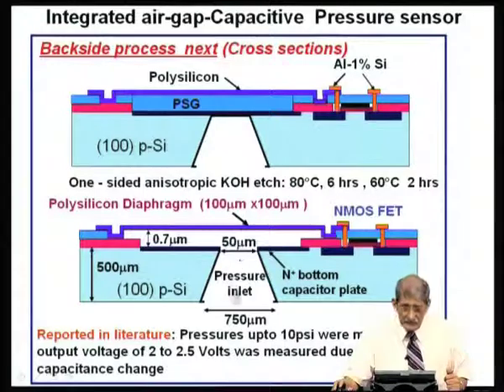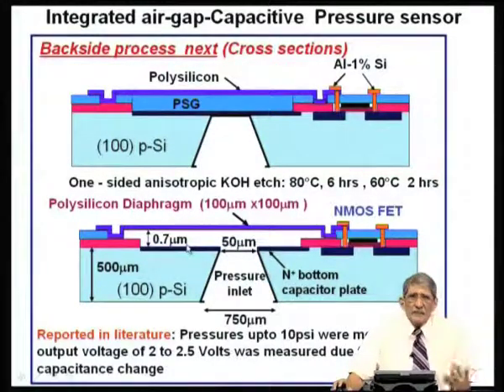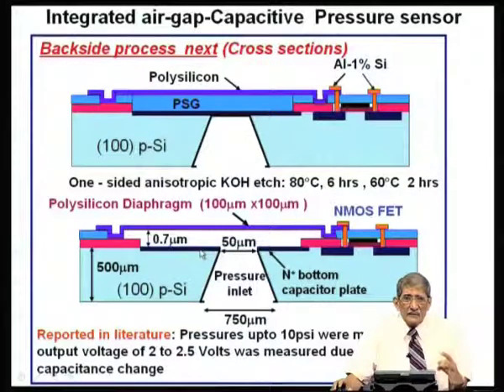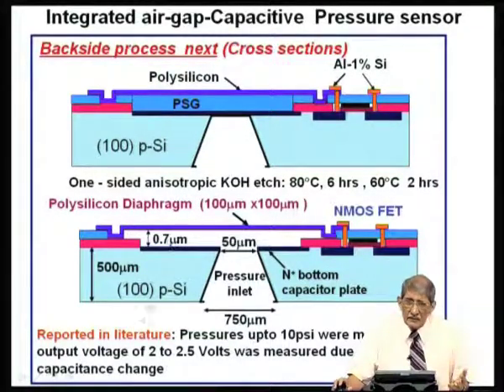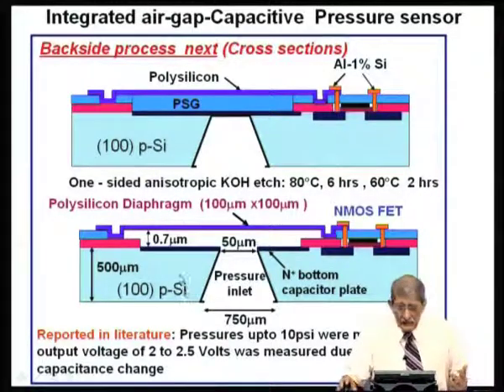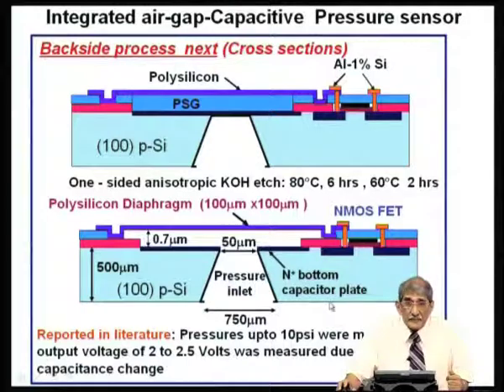You can subject it to stress, pressure is there, this membrane will deflect up, and when it deflects up, the gap between the two increases from 0.7 to maybe 0.71 micron or of that order. Because the membrane deflects up, the capacitance between the two electrodes will decrease because the gap is increased. Capacitance is epsilon A by D. If D increases, capacitance falls. So, the change in the capacitance is sensed using a circuit like the switched capacitor circuit. You can determine the change in capacitance with that or some other circuits. Electronics is used. That circuit is present here. You sense the capacitance change, this is connected together.